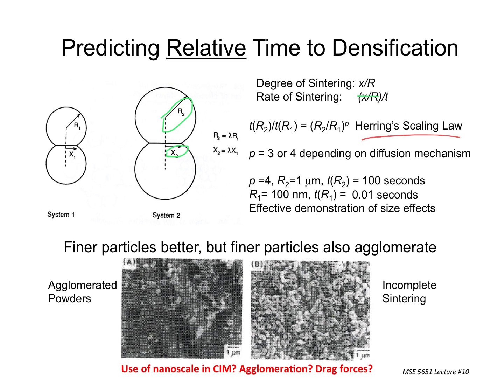And then if you do that as a function of time, x divided by R divided by t, that gives you the rate of sintering. The larger x is, the faster the rate of sintering is. So that's all part of this process. But the whole point here is he developed a law, and there's a huge amount of activity to make it predictive in some way, and it all failed spectacularly.